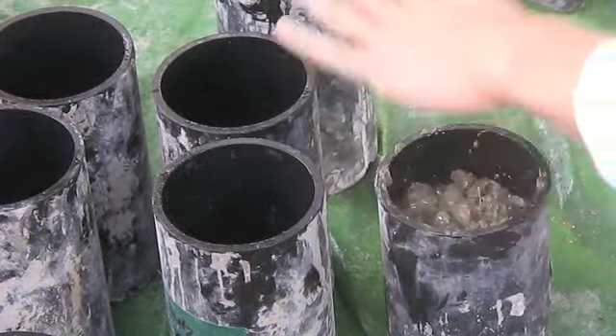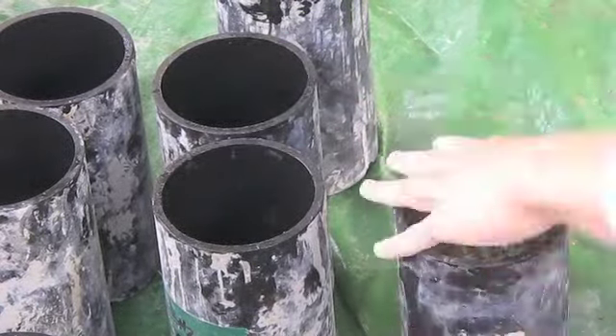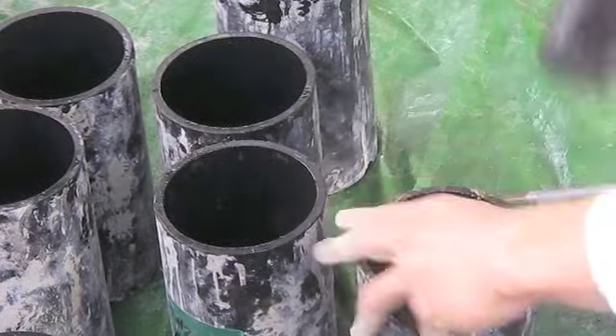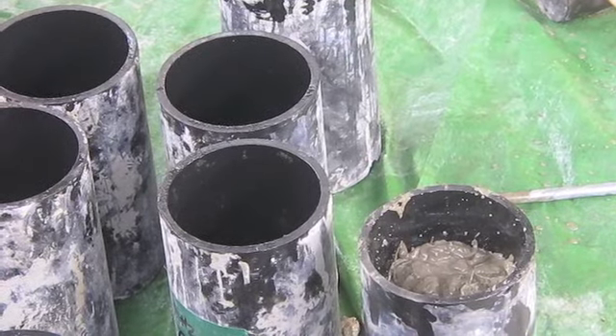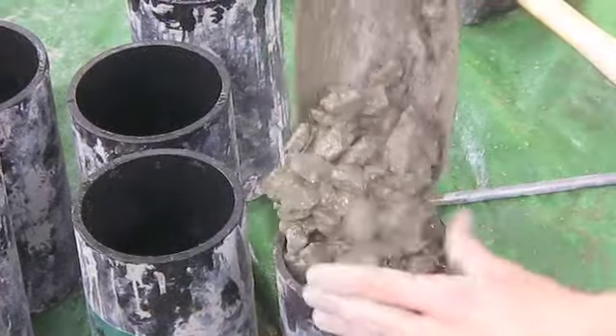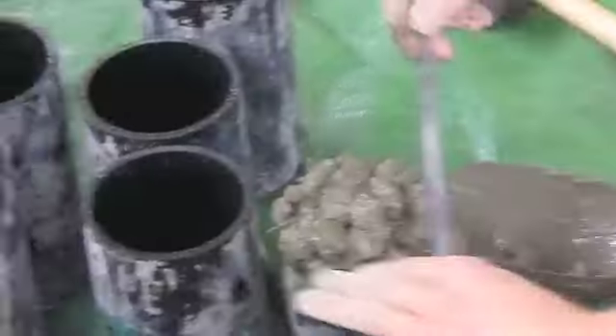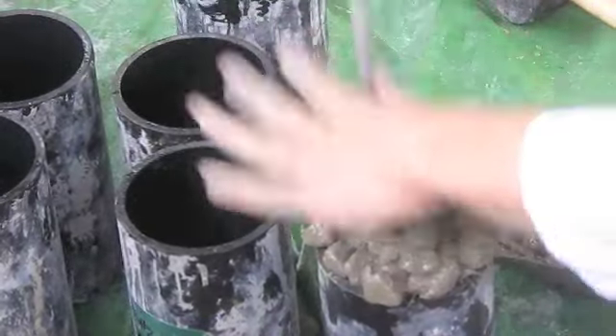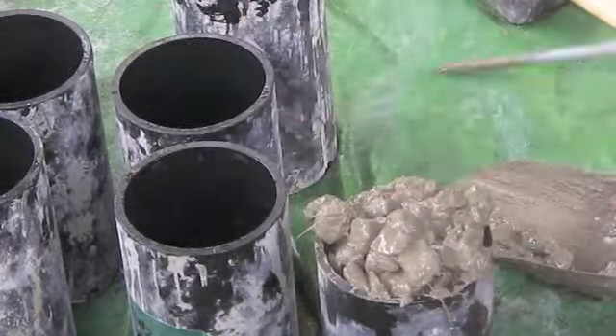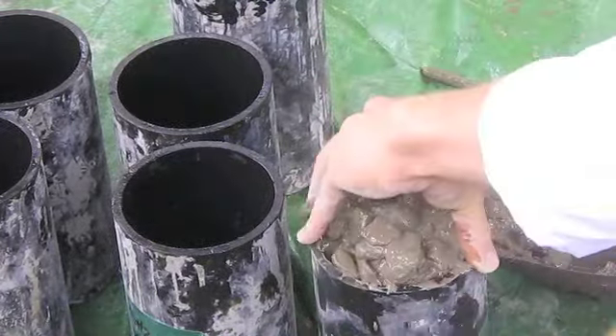With small concrete cylinders, you want to use a small tamping rod, and this time only tamping 20 times per lift. Again, you want to be doing 1/3 lifts and using the rubber mallet on each lift approximately 15 times to consolidate. Do this all the way up to the top, again overfill, and then after your 20 tamps, you want to screed off the top.